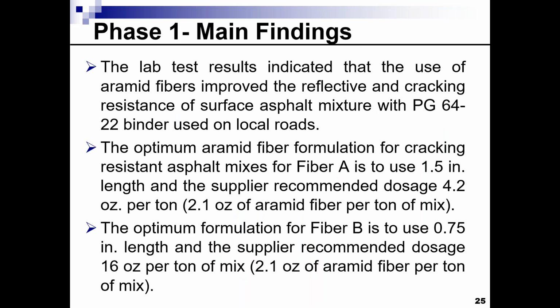What we have from phase one, and again, I'm just putting here the main findings. The detailed findings can be found in the report, which should be published soon. The main thing is the lab study is indicating that the addition of the fiber seems to be improving the reflective and fatigue cracking resistance of the mixture with a 64-22, and specifically a type 1 mix.